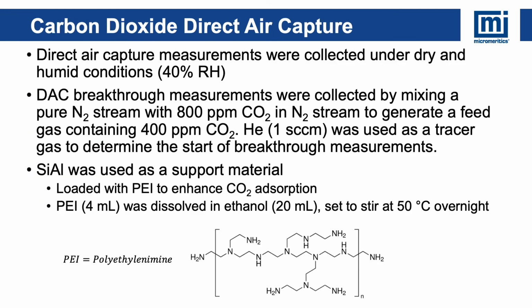The last study I'd like to talk about is some very recent work that I've been collecting on carbon dioxide direct air capture. These direct air capture measurements were collected under both dry and humid conditions, targeting 40% relative humidity. Our direct air capture breakthrough measurements were collected by mixing a pure nitrogen stream with a 800 ppm CO2 and nitrogen stream to generate a feed gas containing roughly 400 ppm CO2.